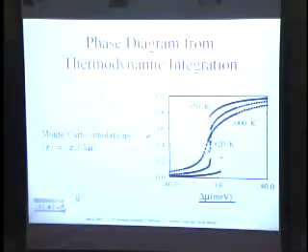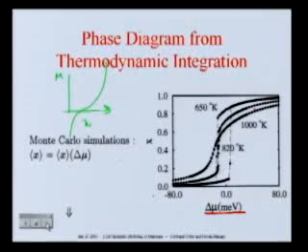That is, there is a region of concentrations from 0.1 to 0.8 that never appear. So at 650 Kelvin, this system doesn't want to mix in the concentration regime between 0.8 and 0.1. And this is typical of model alloys. The miscibility gap is open, the two things don't mix.